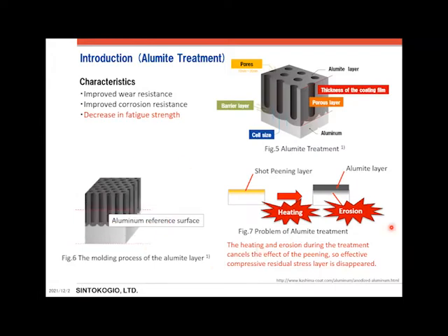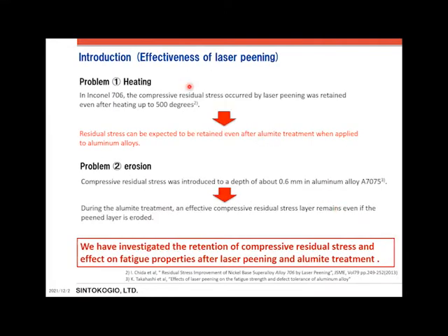In the case of shot peening, the heating and erosion during the treatment cancel the effect of the peening, so the effective compressive residual stress layer disappears. Therefore, we thought that the problem could be solved by laser peening. In Japan, it has been reported that the compressive residual stress introduced by laser peening is retained even after heating to 500 degrees. From this report, we thought residual stress can be expected to be retained even after alumite treatment when applied to aluminum alloys.